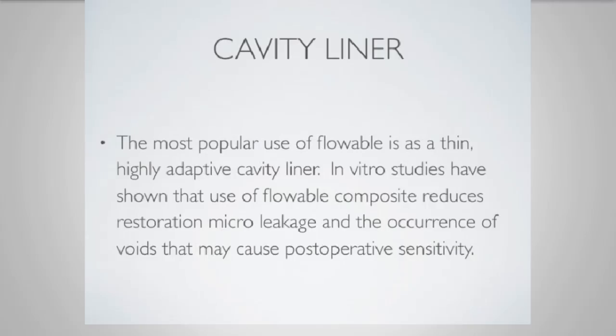So it turns out that the most popular use of flowable is as a thin, highly adaptive cavity liner. In vitro studies have shown that the use of flowable composite reduces restoration microleakage and the occurrence of voids that may cause post-operative sensitivity. Now, a survey was done among 700 dentists in Germany, and it revealed that the majority of dental professionals, 78%, use flowable composites as a liner underneath posterior composite resin fillings. So if you use flowable as a liner underneath your fillings, you are in the majority. But it's 78%. So it turns out it's not everybody does it.